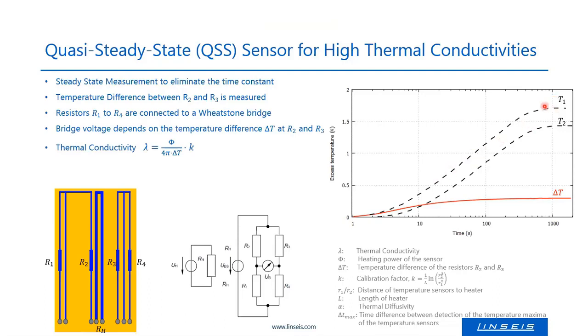Typical results look like that. T1 is measured, and T2. T1 comes from this resistor, which is nearer to the heater, so it goes up faster because it sees the heat from the heater earlier. And T2 comes from the resistor R3. Then the difference between T1 and T2 gives delta T. And the measurement needs to be done until delta T is constant.